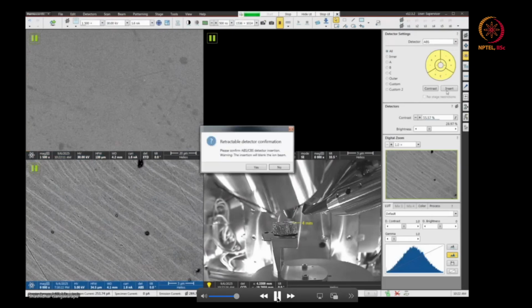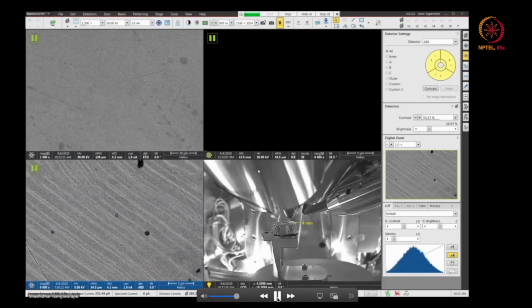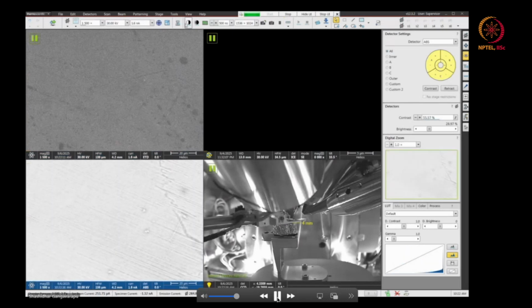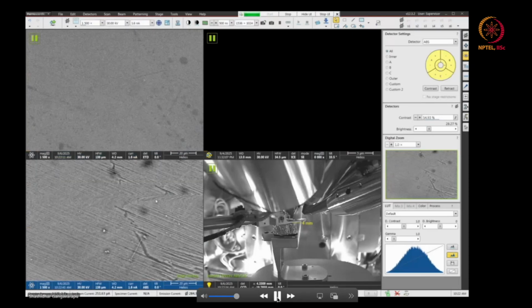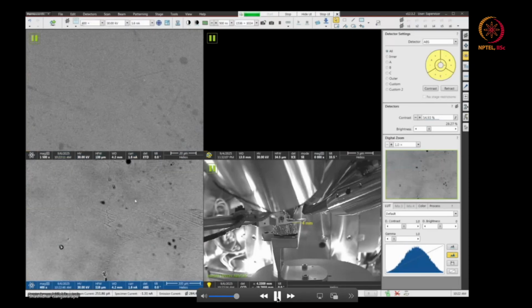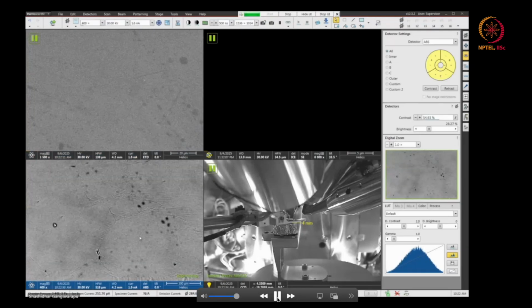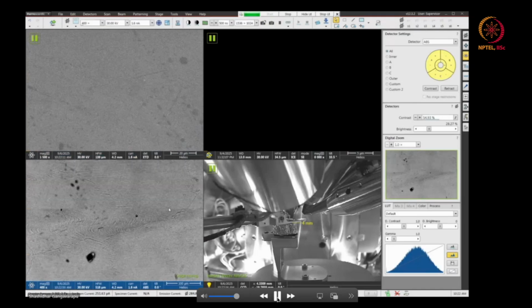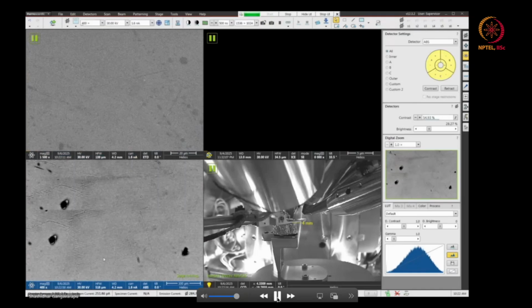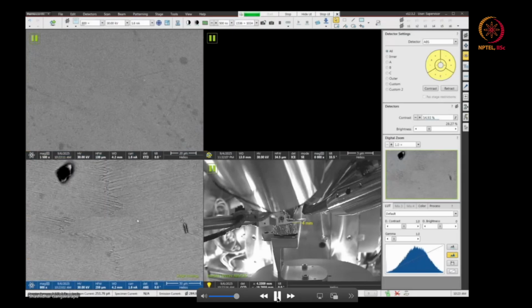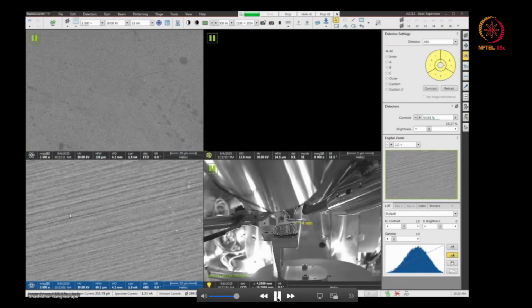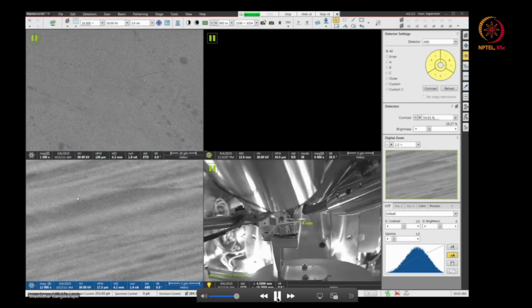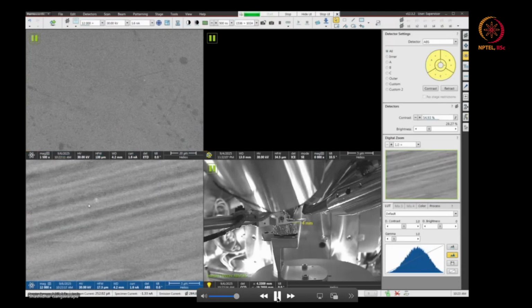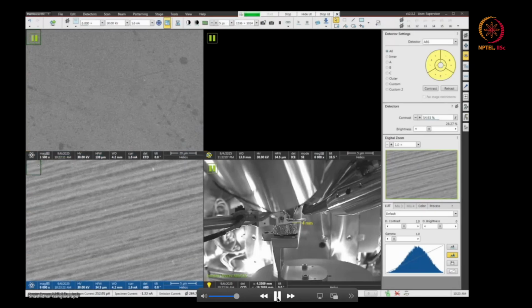Now I turn the NavCam window into an electron beam window. In that window, I will insert the BAC detector, ABS detector, annular backscatter detector, backscatter electron detector. Now you can see the features. In the SE images, my feature is not clearly visible, but in backscatter, it is a good contrast imaging. So you can see nicely two different features, two alternate lamellar plates. The sample is a titanium aluminide sample. The titanium aluminide consists of two alternate plates of Ti3Al and TiAl, and in that window I am doing focusing in backscattered mode.